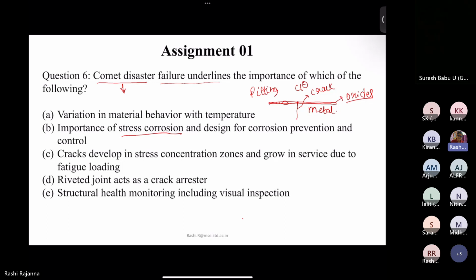But that was not the reason why the Comet failed, right? That was the reason for option B. The crack developed in the stress concentration zone and grew in service due to fatigue loading. As we have seen, the window which was there was well above the limit. Usually the windows that we have in flight are very small.